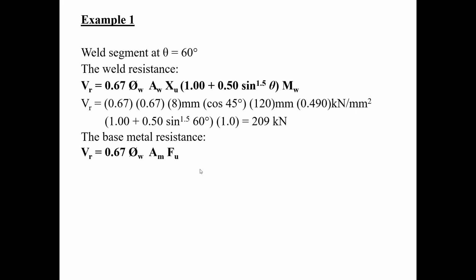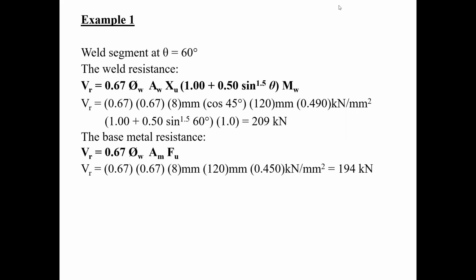And for the base material, I use this equation here. Now, here you see that the base material is weaker than the weld itself. So what they're saying is that when I'm looking at this weld segment, if I look at a cross section here, where the weld is being produced, the fusion face here and the fusion face here are weaker than the weld itself, than this part here of the weld. So this is the one that governs the resistance. In other words, most likely the material is going to break off before the weld breaks. And therefore, you take the smaller of the two. And it's not 209, it's 194.